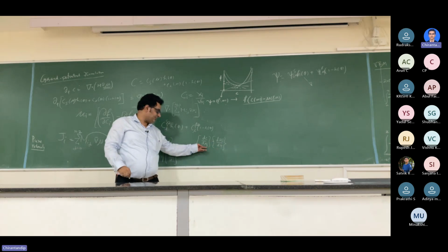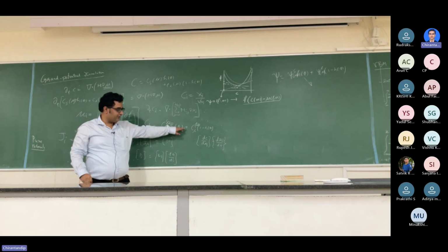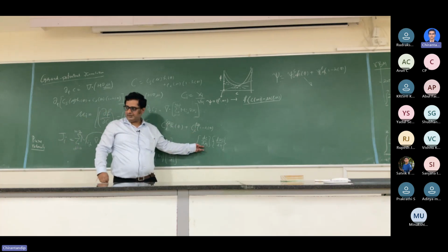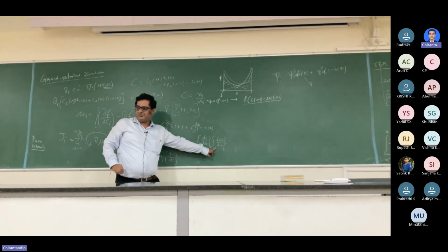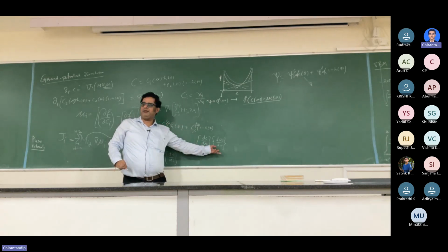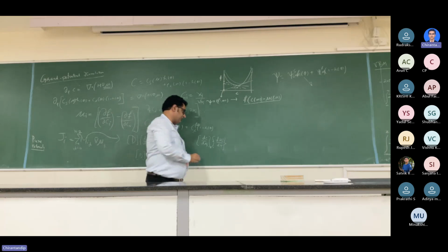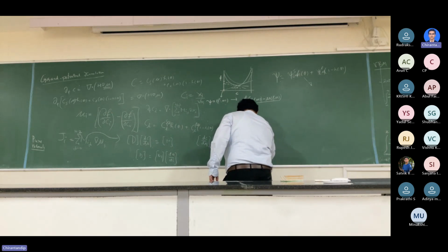And this is essentially the interpolated sum. So I'm going to take dc by d mu times h of t plus dc by d mu times 1 minus h of t, and write it as a total thing, which is a function of t by definition. So this is a matrix multiplied by a vector, which is d mu i by dt. This is equal to del dot